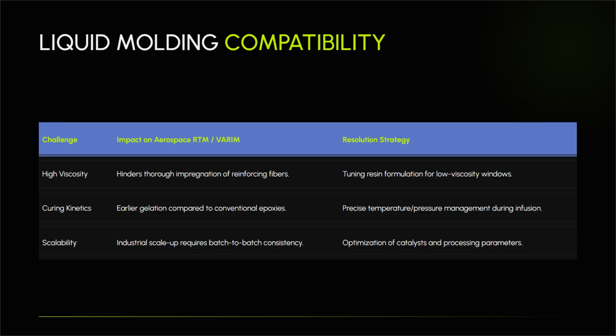The second issue lies in curing kinetics. Vitrimers typically experience earlier gelation points compared to conventional epoxies. This narrow processing window requires highly precise temperature and pressure management during the resin infusion stage to ensure complete saturation before the network locks into place.